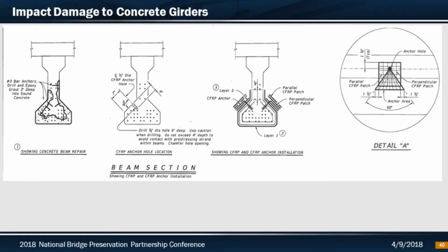This was the detail of the repair. The bottom flange was wrapped entirely from the top of the flange all the way to the bottom, all the way to the other side, and then at each one of the anchor locations, several more bi-directional plies were added with the anchor on top. So it was anchored through the plies and then brought out, again, just increasing the bond strength of that patch and ensuring a longer-term service life. These were the field installed anchors on that particular girder.